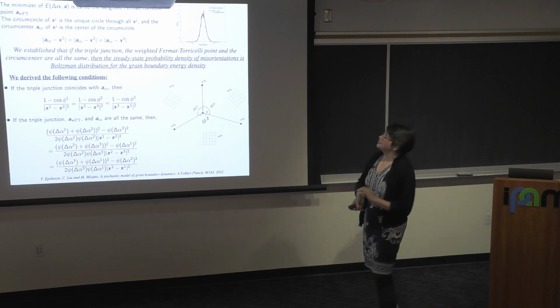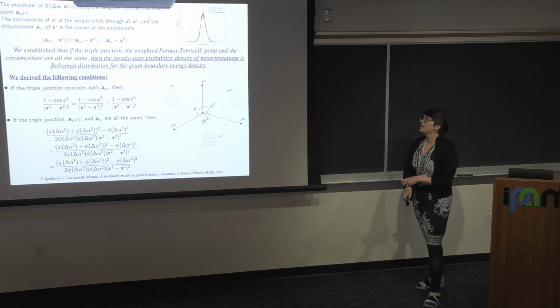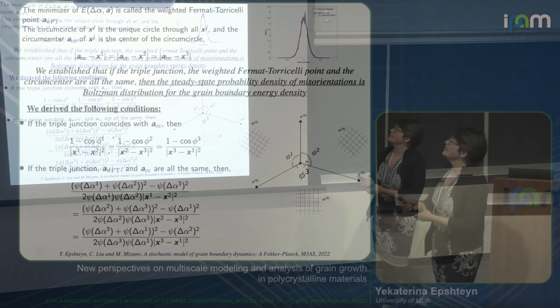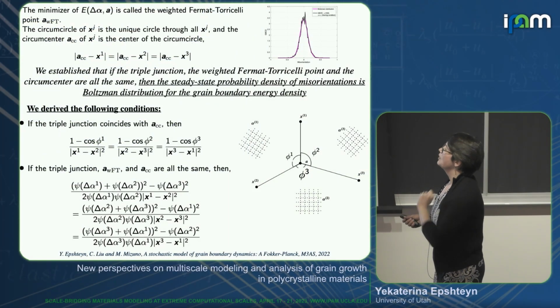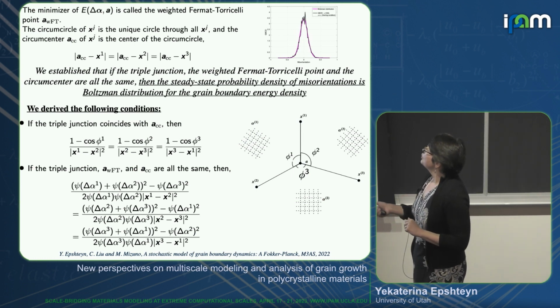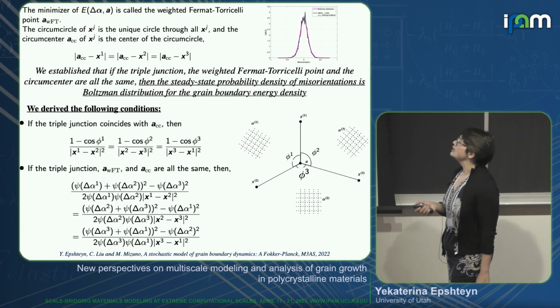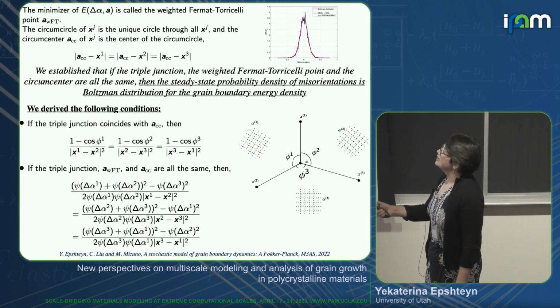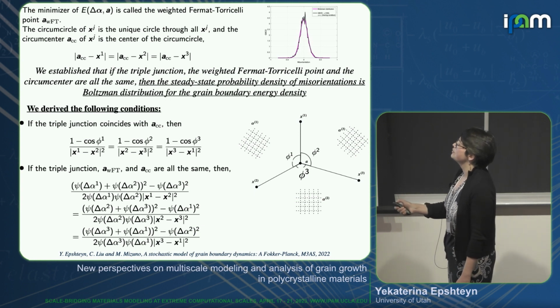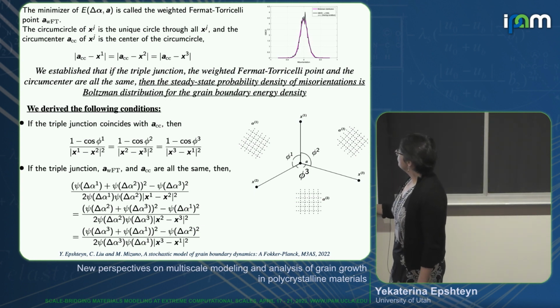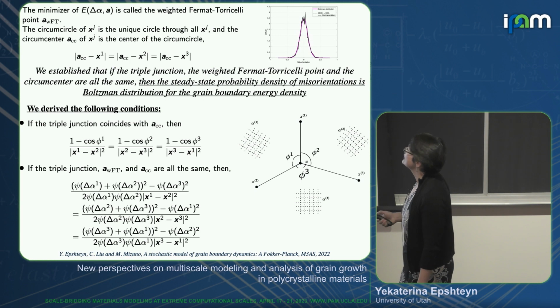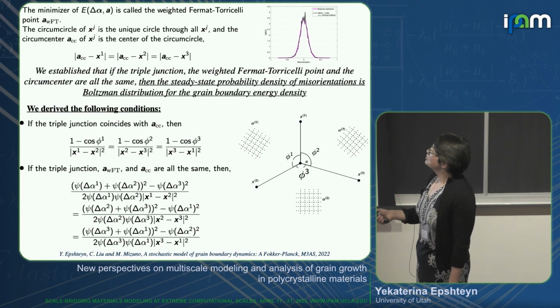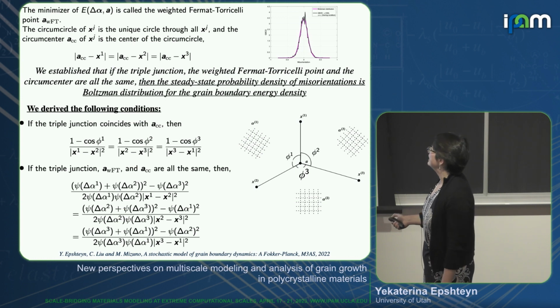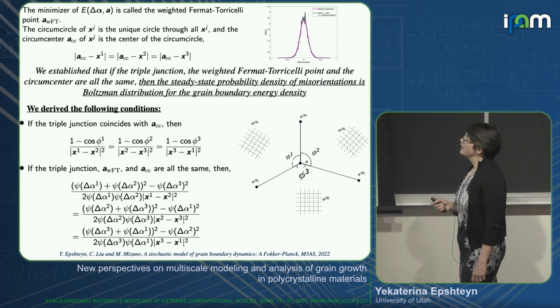And okay, I guess I have a few minutes. And we did derive a sufficient condition, not necessary. And for that, I need to introduce two new points. So a weighted Fermat-Torricelli point, it's basically, for the given misorientation delta alpha, a minimizer of this energy. And also if we mark 3 points along grain boundaries, say x1, x2, x3, we also need to introduce a point which we call a circumcenter. So it's an equidistant point from 3 points along 3 grain boundaries.